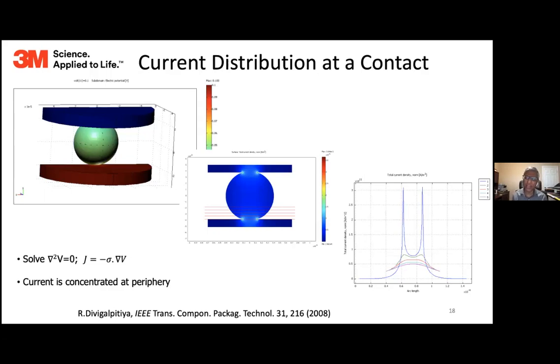When you make any electrical contact, our naive thinking is, okay, the current goes uniformly from one conductor to the other, but the case is very different in real life. Here I have analyzed just a spherical particle between two plane conductors. If you solve the Laplace equation and calculate the current density, you get very surprising results. This is the plot of current density. I'm using finite element analysis here. You see about 4 hotspots in that two-dimensional cross section. In reality, you have to rotate this about the vertical axis. Then what you get is a circle of high current at the electrical contact between the spherical particle and the plate. So it's not very uniform. There's a huge current spike at the interface. 80% of the current flows in that region.